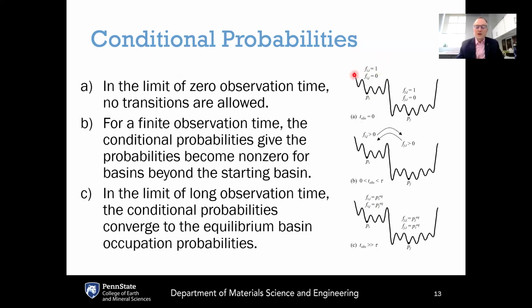Likewise, if you have zero temperature, then no kinetics are going to occur. On the other hand, at the bottom here, if you have the limit of very long observation timescale, this is consistent with the ergodic hypothesis because in the limit of infinite time, it doesn't matter where you start. Equilibrium has no memory. And so for the system after it's equilibrated, the conditional probabilities become the equilibrium probabilities of that final basin. They no longer depend on where you start. So this would be a fully ergodic system that has been equilibrated, and this is captured in the limit of long time scales in this framework of continuously broken ergodicity.